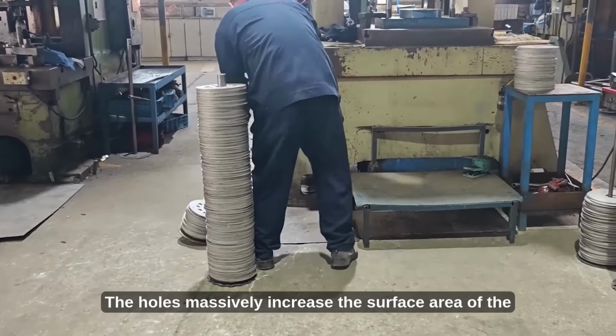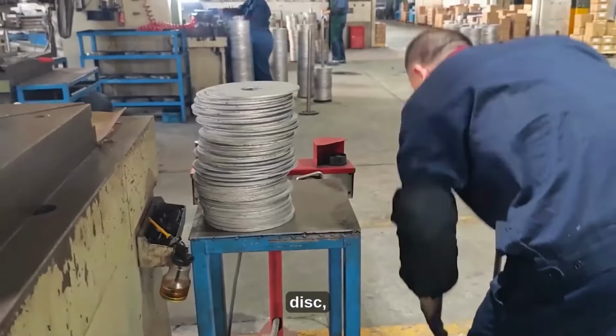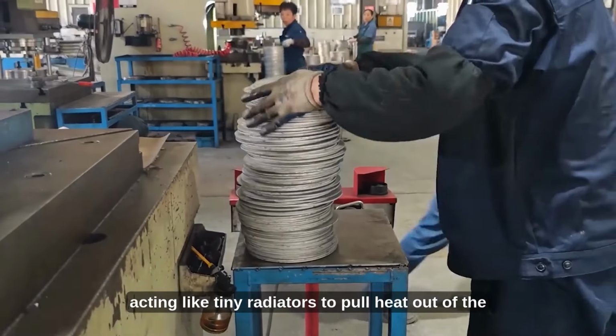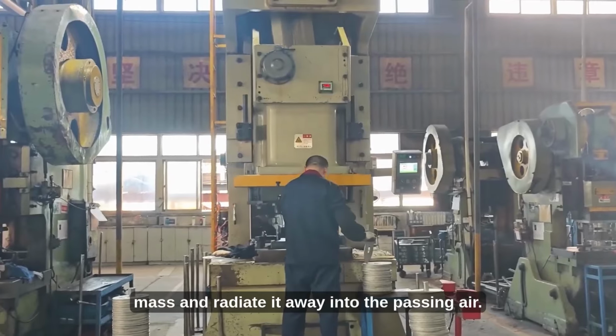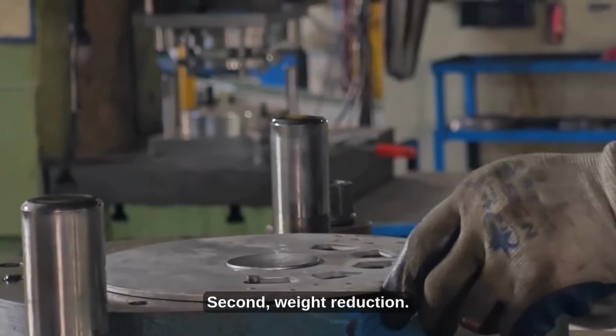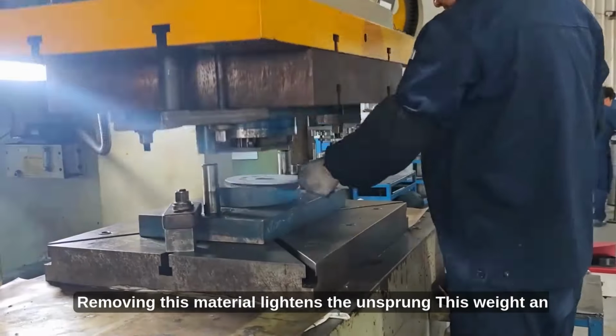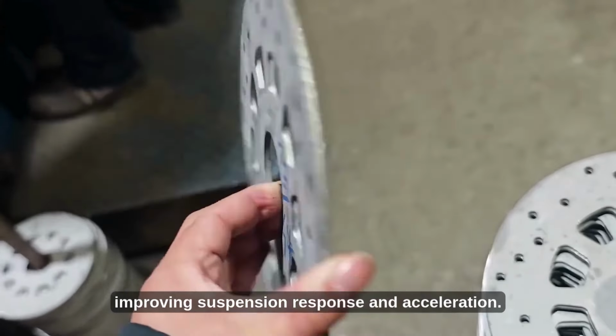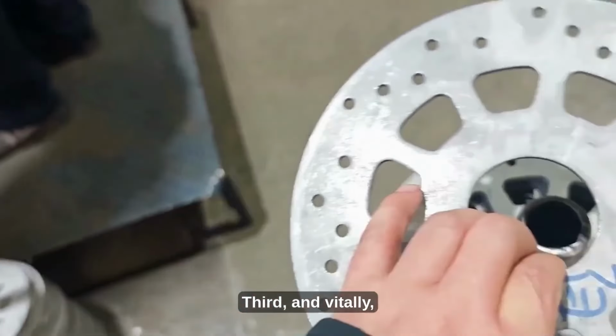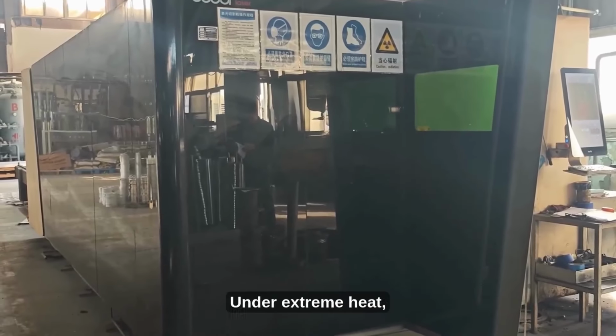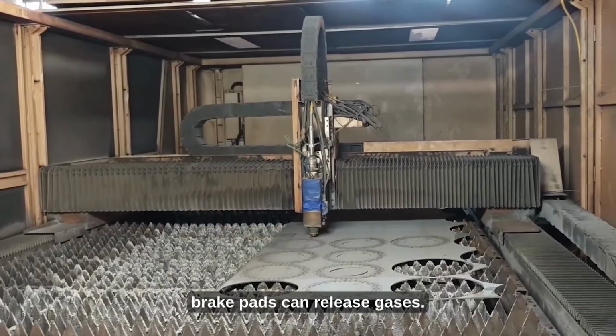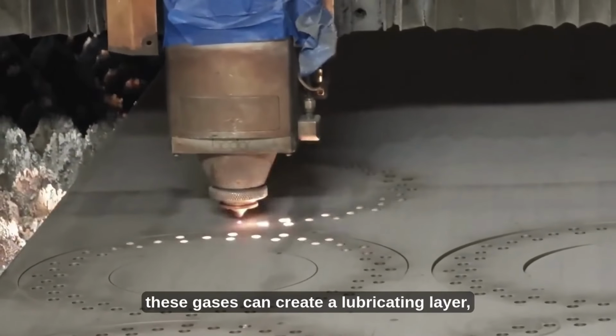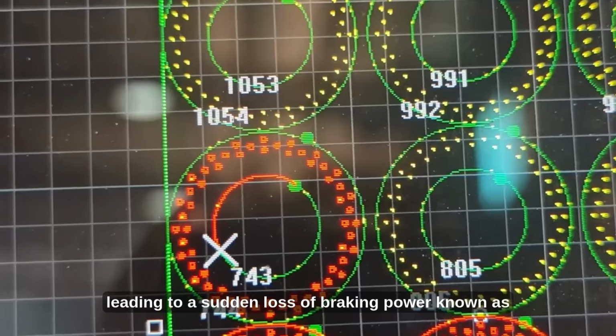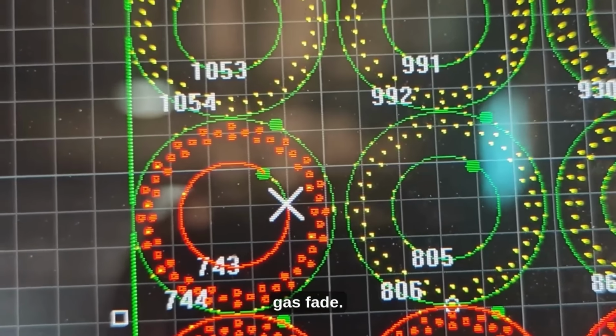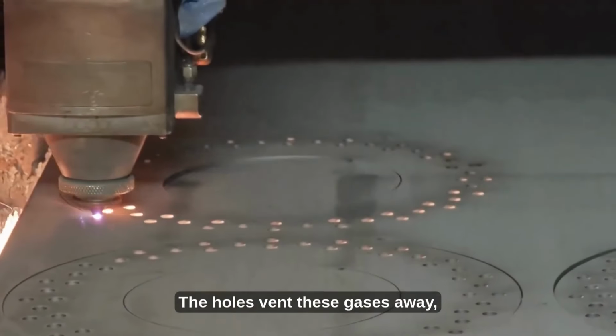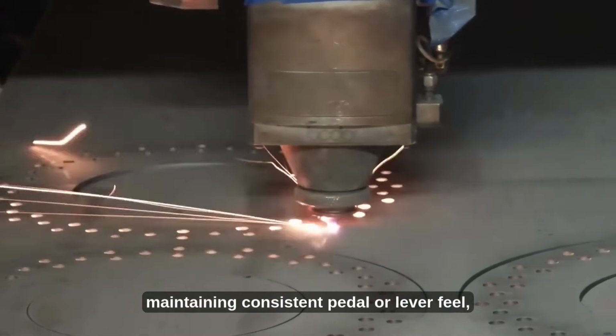First, heat dissipation. The holes massively increase the surface area of the disc, acting like tiny radiators to pull heat out of the mass and radiate it away into the passing air. Second, weight reduction. Removing this material lightens the unsprung weight and the rotating mass, improving suspension response and acceleration. Third, and vitally, they provide an escape route for gases. Under extreme heat, brake pads can release gases. If trapped between the pad and disc, these gases can create a lubricating layer, leading to a sudden loss of braking power known as gas fade. The holes vent these gases away, maintaining consistent pedal or lever feel.